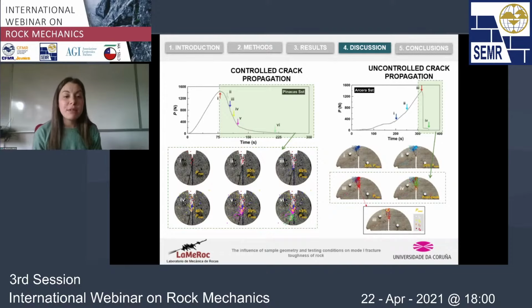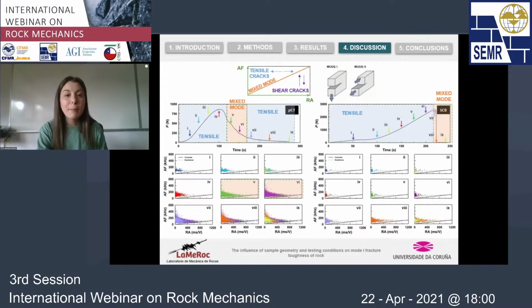Also, we have used the acoustic emission setup to locate the events during the experiments. In the case of the PCT, here we are plotting the events from the peak load. At this point, we observe that they are mainly concentrated here at the notch tip, and then as the fracture propagates and the load decreases, we observe that these points extend along the ligament plane, and at some point they start to deviate towards the left, and this one is following the actual crack in the material, which is this one here. In the case of the SCB, we don't have as much information, and we observed that from the beginning of the experiment, there is a huge concentration of acoustic events on the contact with the top roller, and when the fracture propagates, all the events are located along the ligament plane.